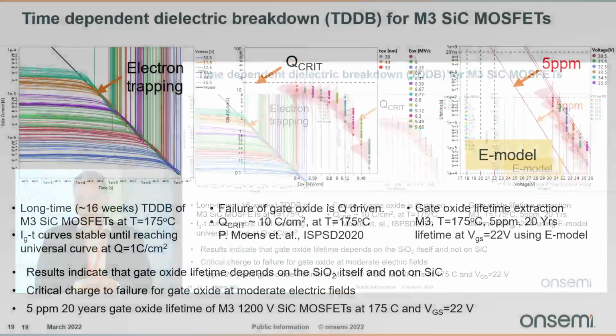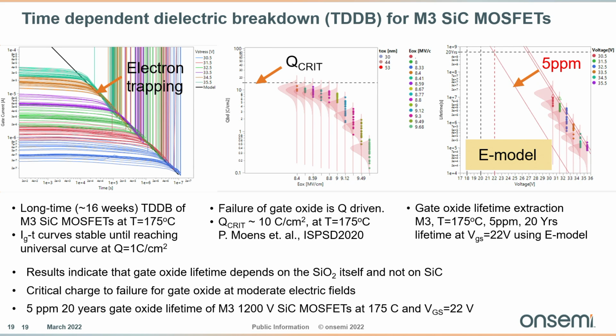Then important for the gate oxide lifetime is the time to fail. We do time to failure measurements here. These run for a very long time. Here we have the M3 from 30.5 up to 35.5 volts. Monitor current versus time until we get failure. And we can see that we start to get electron trapping after a charge of about 1 coulomb per centimeter square here. And we can then see a critical